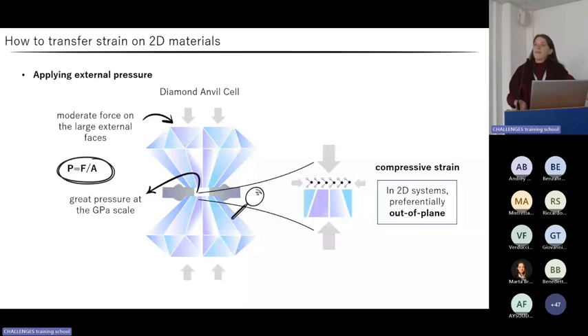In the case of two-dimensional materials, low-dimensional flakes are mechanically exfoliated in most cases, and then transferred onto the culet of one of the two diamonds by a deterministic transfer system. Then pressure is applied, squeezing the crystals against each other, often with the help of a pressure transmitting medium, which can be either a gas or a liquid. Due to the highly anisotropic nature of intralayer and interlayer bonds in two-dimensional materials, the application of pressure on these systems mostly results in a compressive out-of-plane strain component.